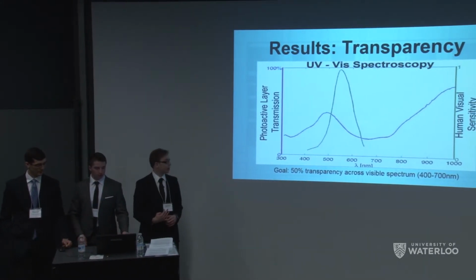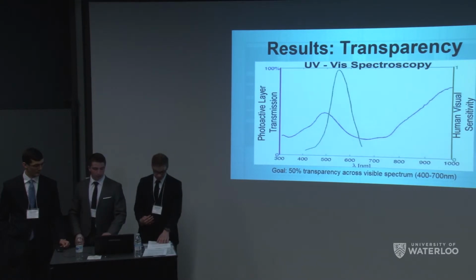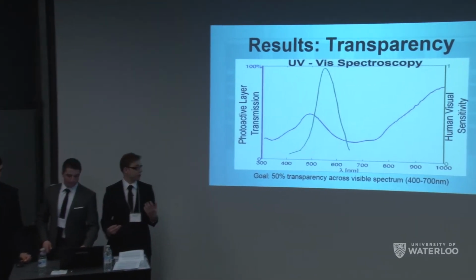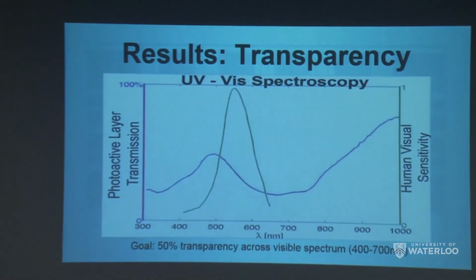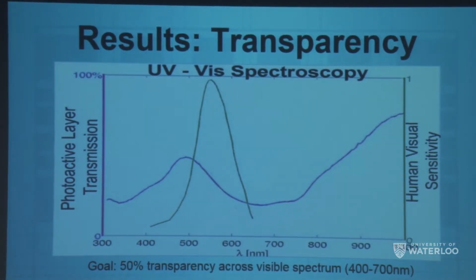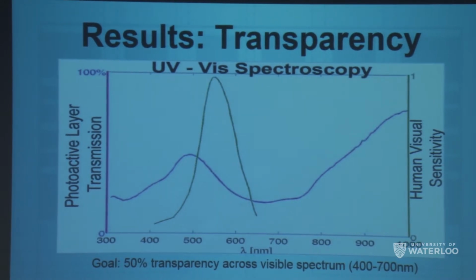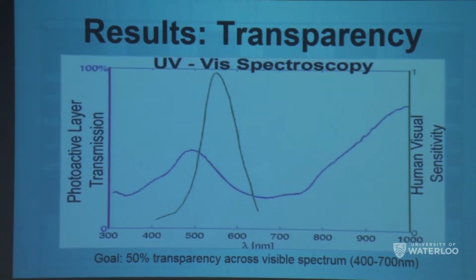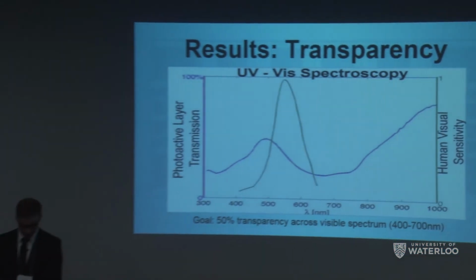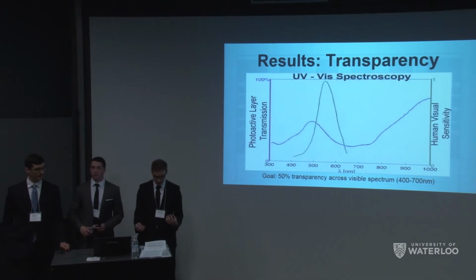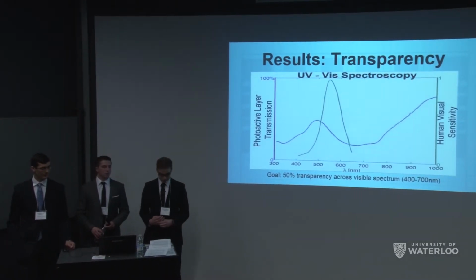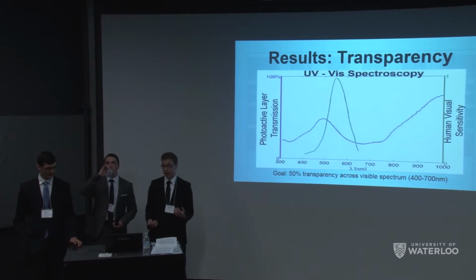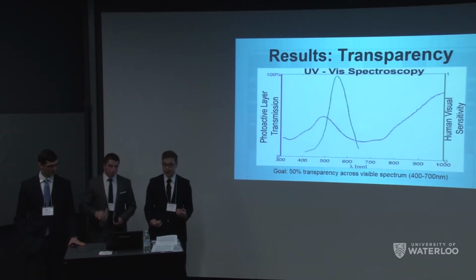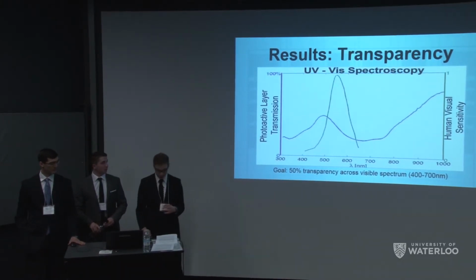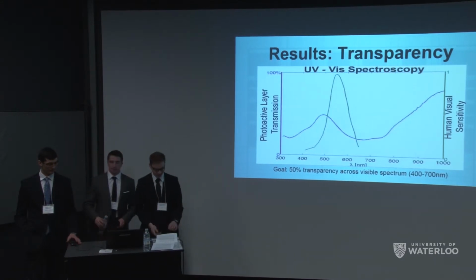If you take a look at this plot of the device's actual absorbance spectra, you can see that we actually had very good transparency. Though we absorbed a little bit more in the red than we would have liked, we actually believe that this could be improved by having a better annealing process, as this could lead to pi-pi stacking internally, which would lead to shifting this peak further into the infrared. This is also an issue that could be addressed with different photoactive polymers. As the chemistry catches up to the engineering, different polymers with different absorption spectra could be used. Another point of note is that not all exterior glass is totally transparent. Adding tints to these devices could make them more powerful, as well as more appealing to our friends in architecture.